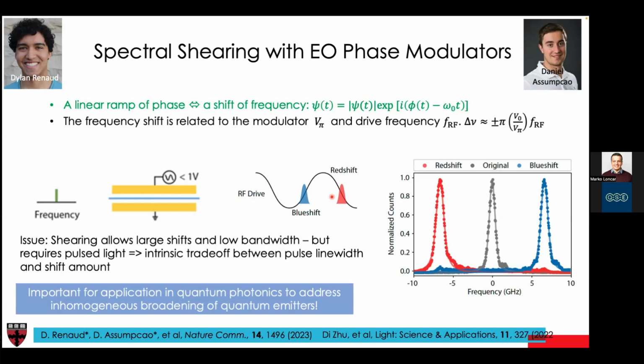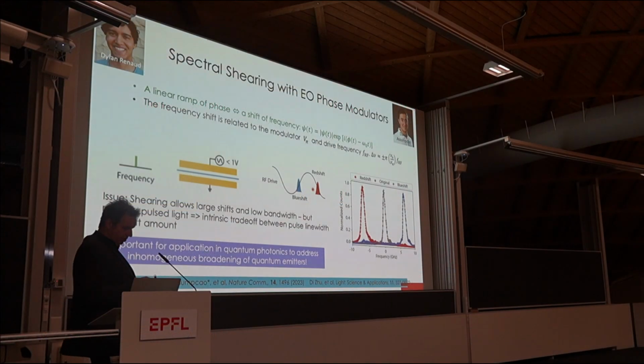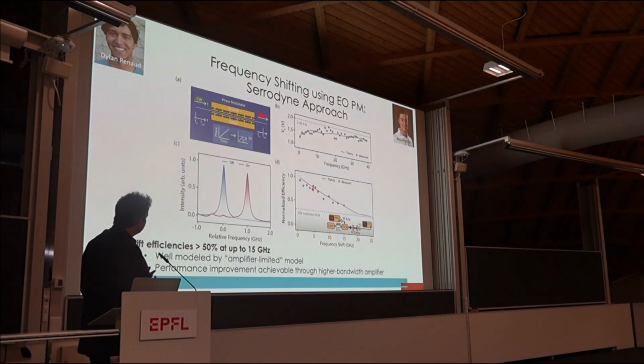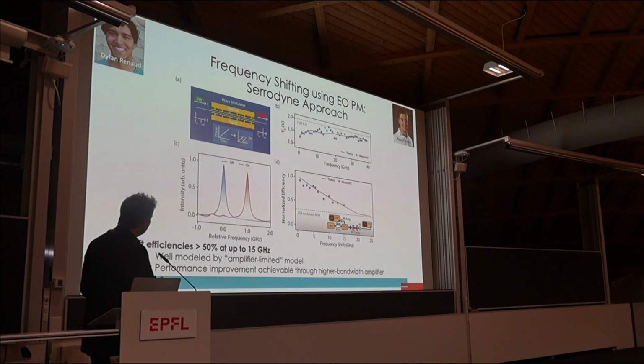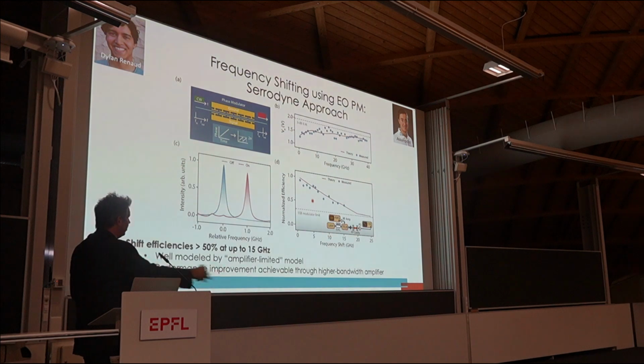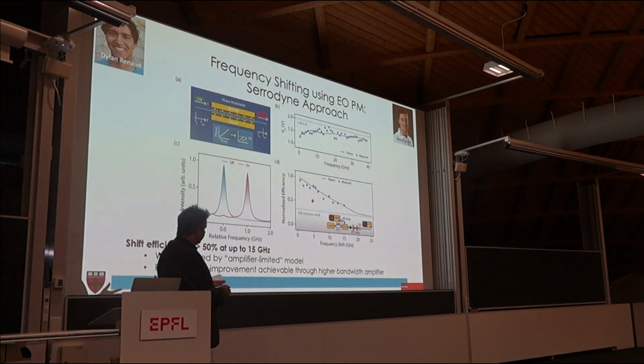But the question is, can I do this with CW light, which is kind of what our single photons are, a little bit like continuous wave light? And then you can use this serrodyne approach where we use a sawtooth. Okay, and then we can get really nice shifts on the order of gigahertz. We have almost no loss, and we can have shifts up to about 15 gigahertz in this case. But this is not a quantum signal, okay, we're shifting the color of a CW signal.